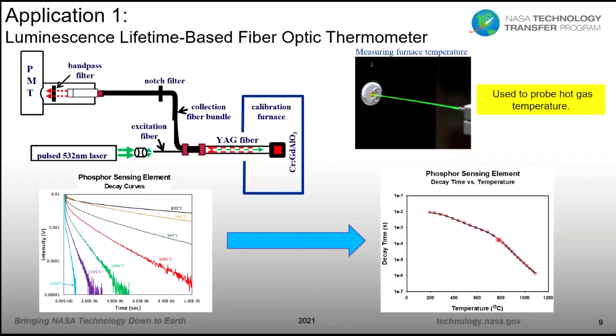And you can see this, again, this thermometer with this material is best for temperatures above 800 degrees C. That's where it has its best sensitivity. Again, I would add, if you're looking for lower temperatures, you might pull back and go from gadolinium aluminate to yttrium aluminate, where the highly temperature sensitive range is at somewhat lower temperatures.